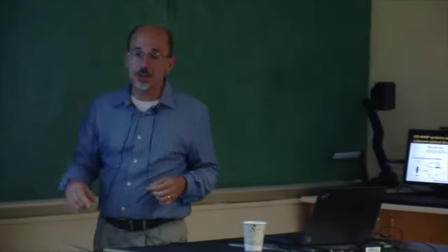Or, another interesting subject: all of us know that when you have a metallic nanoparticle, the plasmon decays in about 20, 30 femtoseconds, and the quantum dot decays in about 400, 500 femtoseconds. We studied this, and we showed that under certain conditions you can send two CW lasers, meaning continuous wave light, not pulses, where the amplitude doesn't change, and then you can see that the near field, the plasmonic field of the metal, starts to oscillate by itself.